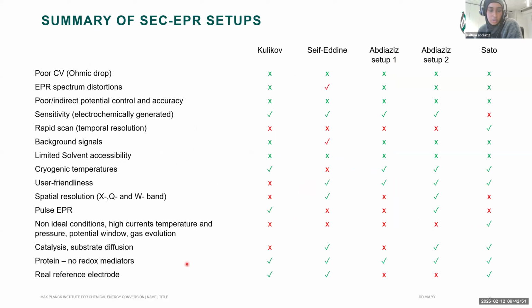So to summarize all the setups that I've shown you, and some from the literature, here are some characteristics that I think are important for the setup. You can see that, at least for the CVs, all setups work very nicely, but there are some distortions in some setups over the others, depending on how easy it is to put your sample inside the EPR spectrometer. Sensitivity is also an issue for some setups and not for others.